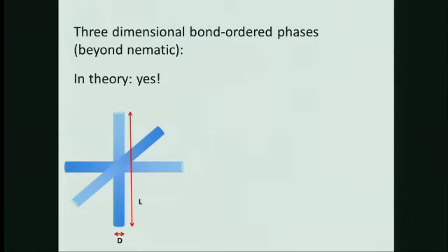If you could make a particle that is 3 perpendicular rods, and you go to the Onsager limit, which means infinitely thin, infinitely long rods, then at some point these particles start feeling the excluded volume of each other, but because they are in the Onsager limit infinitely large aspect ratio, the volume fraction occupied by these particles is still vanishingly small. So these particles can't freeze because that they only do when they occupy a large fraction of the volume. They do get excluded volume effect, and actually they can't form a nematic phase because there's no preferred direction. So all 3 axes in this case are equally long. And so what they actually do, they'll form a cubatic phase, a phase with, if you wish, in the Legendre polynomial language, a P6 orientational, or actually a 6th rank bond orientational distribution.